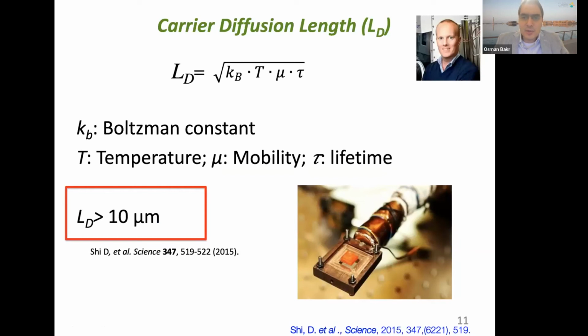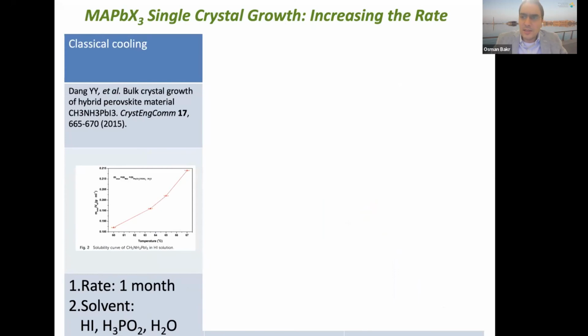And one of the first things we did was try to estimate the charge carrier diffusion length. We couldn't measure it directly, so we measured the mobility and the carrier lifetime, and then used the Einstein relationship to estimate the diffusion length. What surprised us was that the diffusion length of single crystals turned out to be on the order of tens of microns, about 100 times longer than what people thought when they were measuring thin films. So that was a big change in the way the field started thinking about perovskites, and they realized that if we improve crystallinity, we could improve the performance of solar cells significantly, and that's what happened actually.